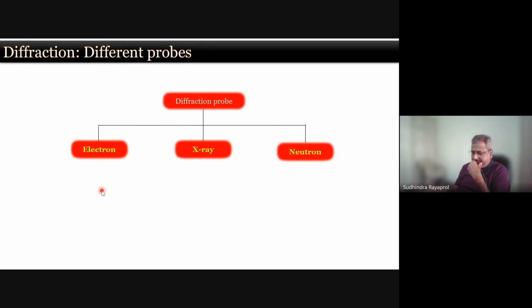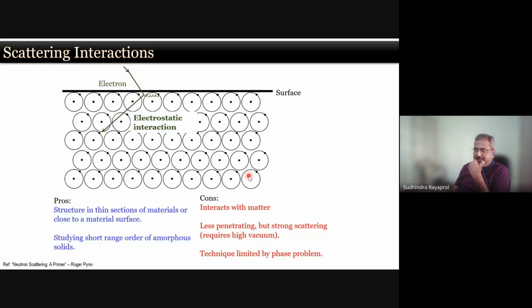So to do the structural analysis, you need different probes. The kinds of probes available are either electron, where you can do electron diffraction, X-ray diffraction, or neutrons. In case of electron diffraction, you are looking at a very point source because of the electrostatic interactions. You can scan the surface in thin sections and very close to the sample surface. It is useful for studying the short range ordering. We are looking at a very small area of a few nanometers or micrometers, and you can understand how the dynamics is, how the structure or layering is, what the morphology is in that small region.